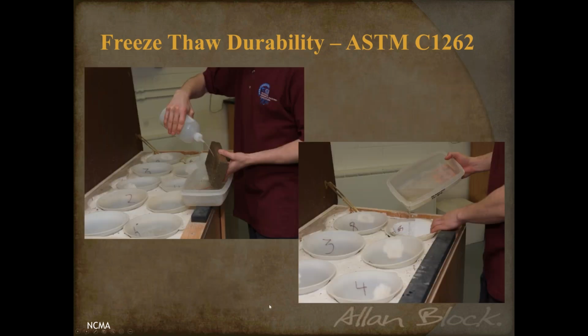In the ASTM C1262, there's a very particular set of guidelines on how to test it. After a certain number of freeze-thaw cycles, the coupon is taken out of the chamber and rinsed off. Then all of the residue that's rinsed off is collected in these coffee filters, and they can actually weigh the material, and that helps them come up with the weight loss.